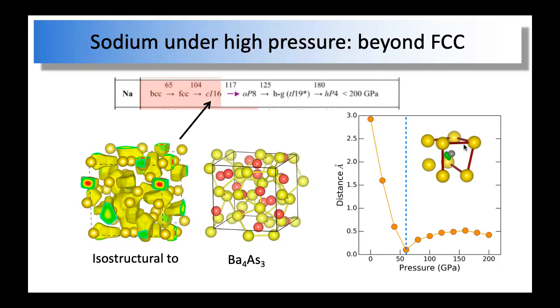If you calculate that for the two subsets, then you can find the electron localization maximum is actually shifted away from the exact location of the atom from the other subset. So this is the driving force. The system wants to avoid this repulsion, this subset repulsion.